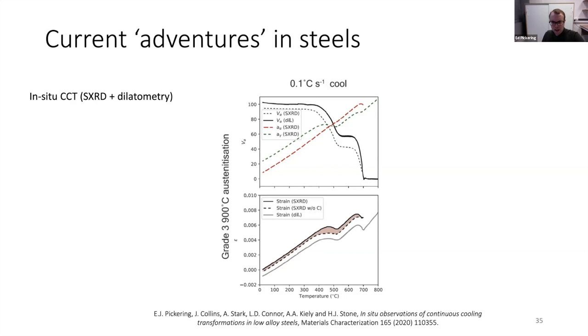So I'm going to explain some interesting things in this data here. We've got the ferrite lattice parameter, and this is when ferrite first starts forming. And you see here we've got two transformations: the transformation to allotriomorphic ferrite at this cooling rate, and then a transformation to bainite later. I should also explain, this is the dilatometry curve, which goes to basically 0% as we cool down in temperature, and we get 60% ferrite here. And then we've also got the same measurement, the fraction of ferrite, from synchrotron as well.